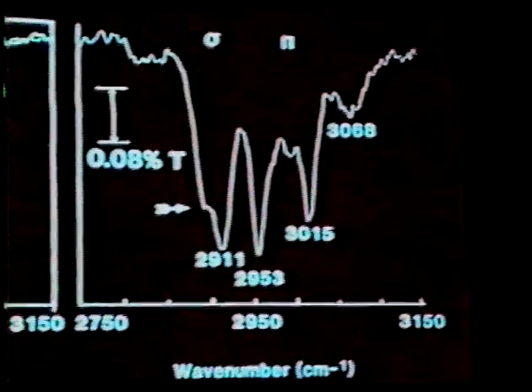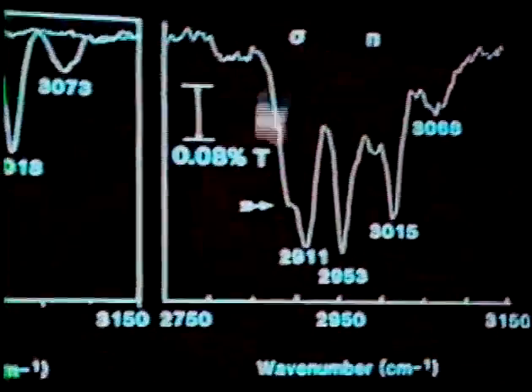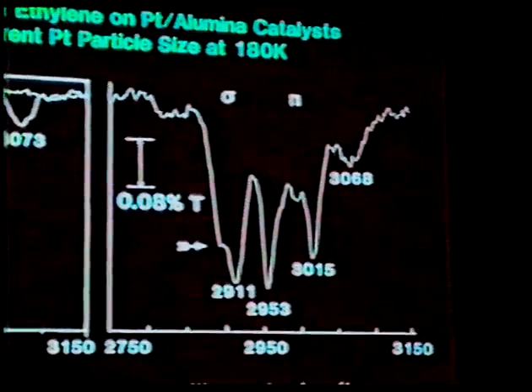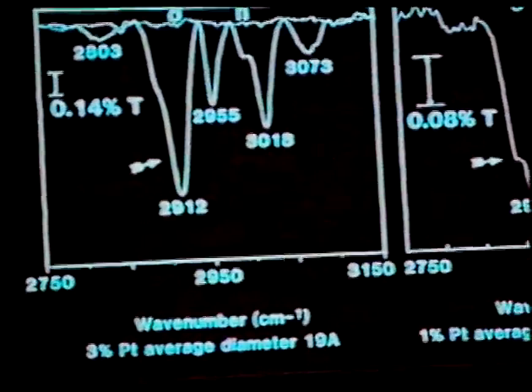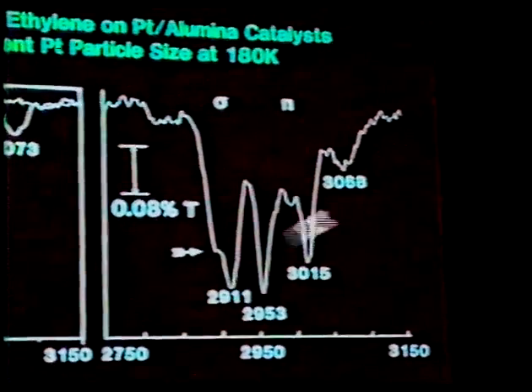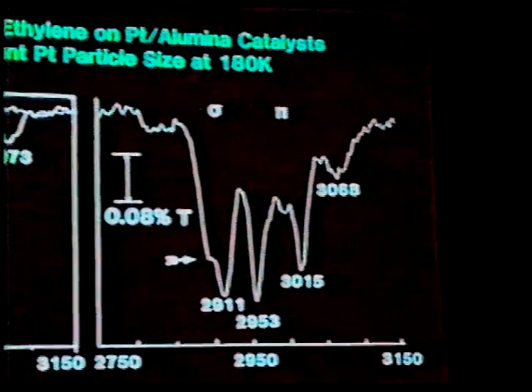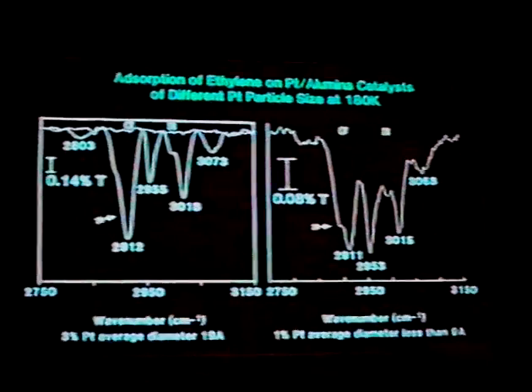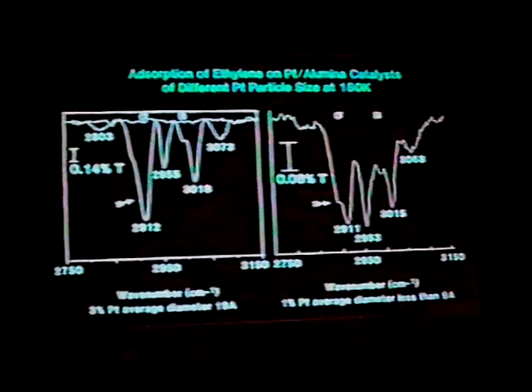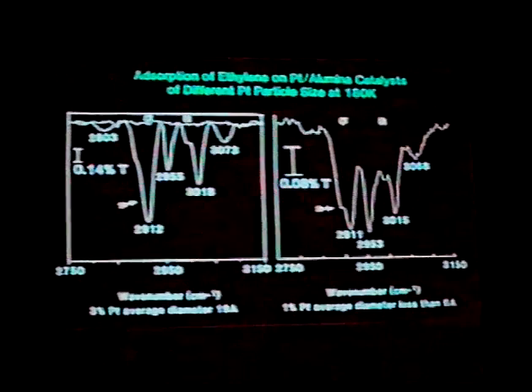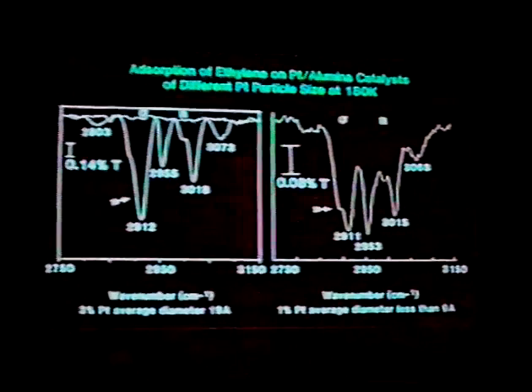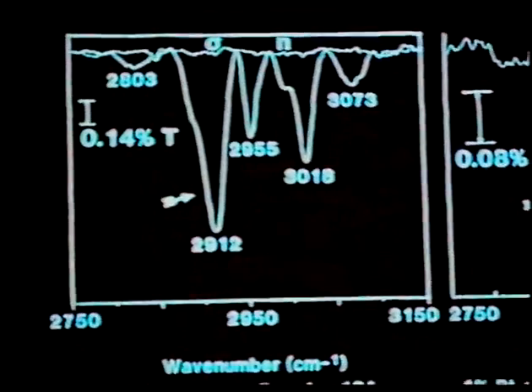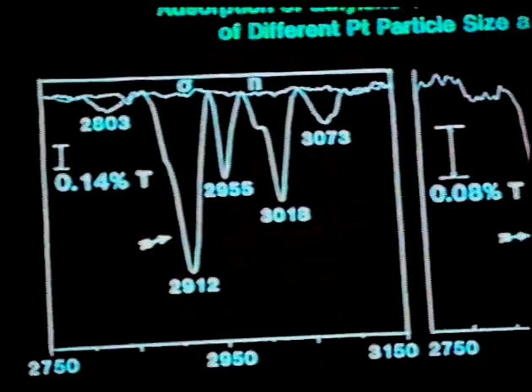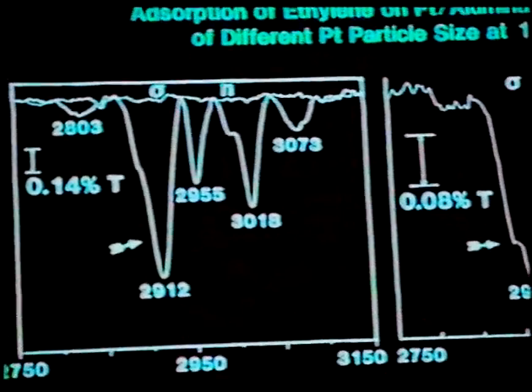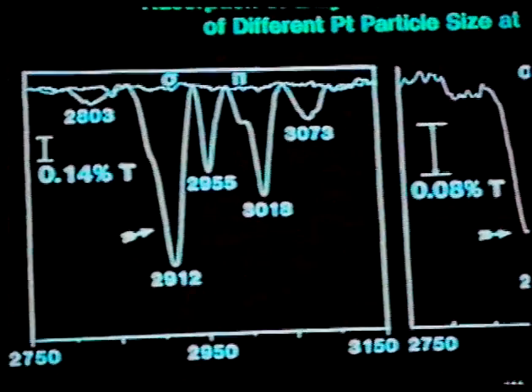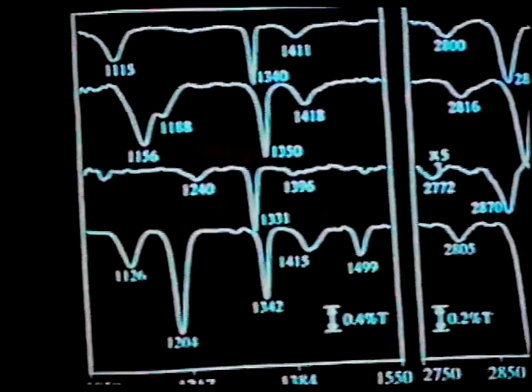And what you can see is, as you might expect, as you decrease the population of the planar types of sites and increase the relative amount of the edge sites, the relative amount of the di-sigma-bonded species decreases relative to the pi-bonded species. At this point, you can be brave. You can thermally abuse one of these catalysts at 800 degrees for many hours, making the population of particles tend toward the larger size. If you do that, under room temperature adsorption conditions, you see exclusively ethylene; you're unable to detect any pi-bonded ethylene whatsoever. So this lends some support to the idea that the pi-bonded species may in fact be formed at the edges between those planes, and the ethylene is being formed on specific planar surfaces. With all that in mind,